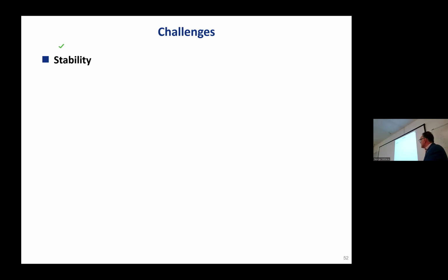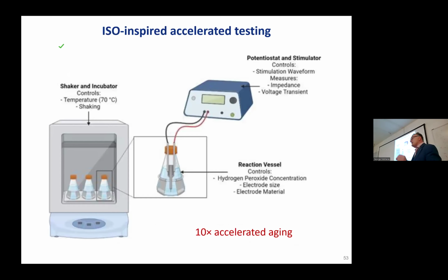What are the challenges? There are some formidable ones, including stability. As these electrodes are very thin, a small loss of mass can devastate your device. So to learn how this works, we set up ISO-inspired accelerated testing where we take implants, we put them in media that are spiked with peroxide to simulate the reactive environment that is caused by implantation. We heat the media up to 70 degrees. That gives you approximately 10x acceleration in terms of time.